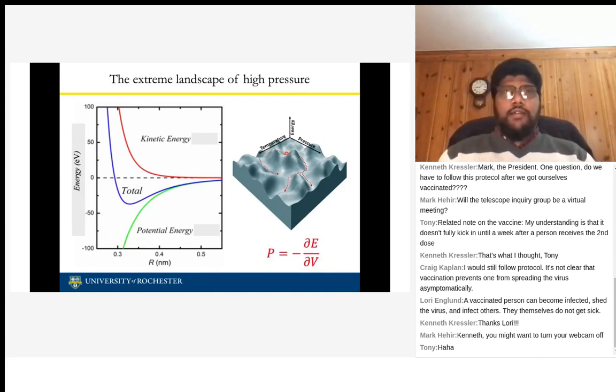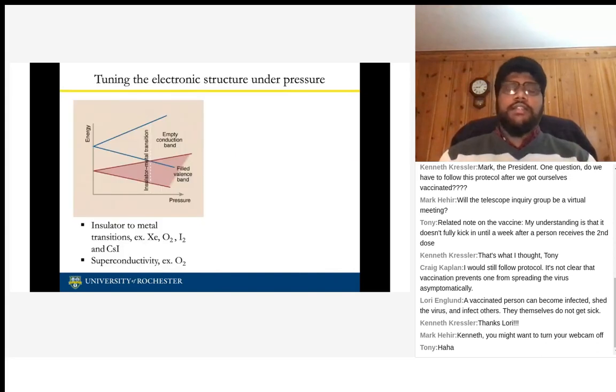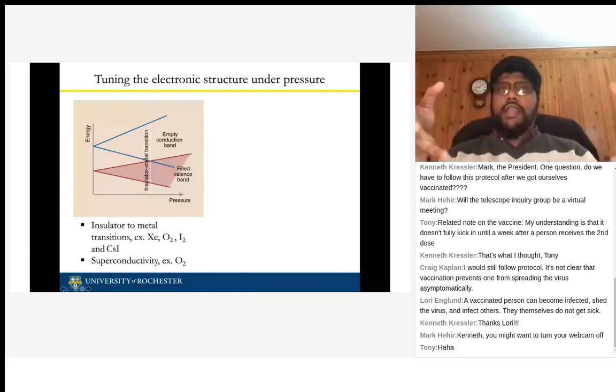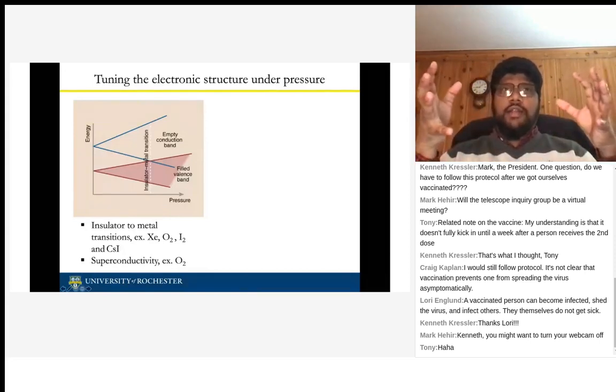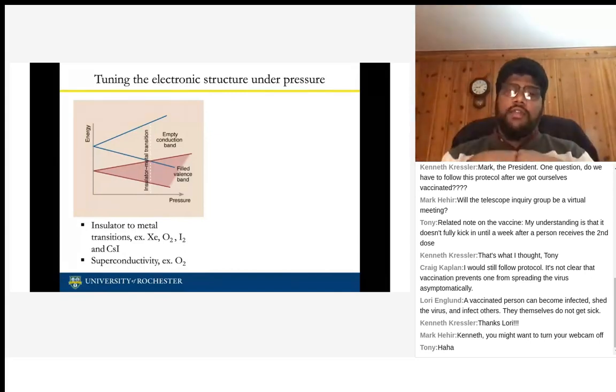And then another phenomenon is this. If you take an electrical insulator, which means that you have a band gap, this is a very simple picture. I'm showing pressure versus energy. You have a valence band and you have a conduction band. So in an insulator, you have a gap. But when you pressurize it, these bands get broader and broader. At some point, they're going to overlap, and that's where you can have an insulator-metal transition. Which means that you can take an insulator and with pressure, you can make a metal out of it.